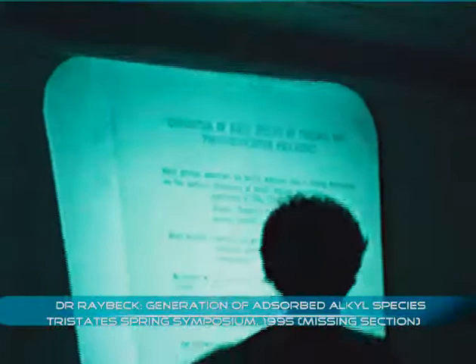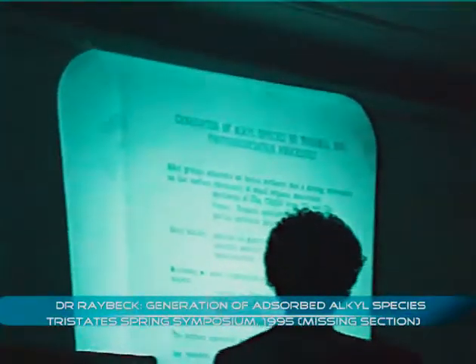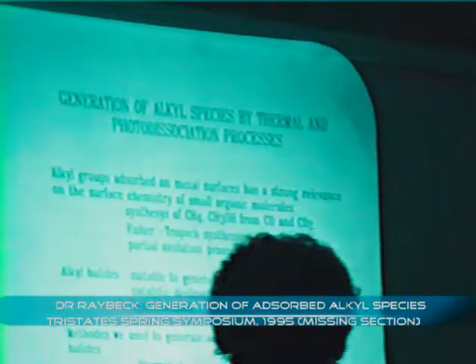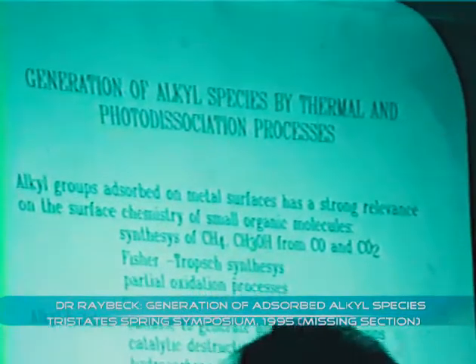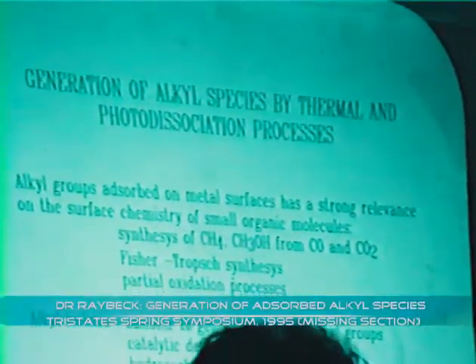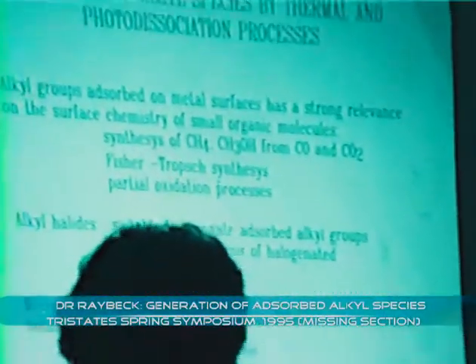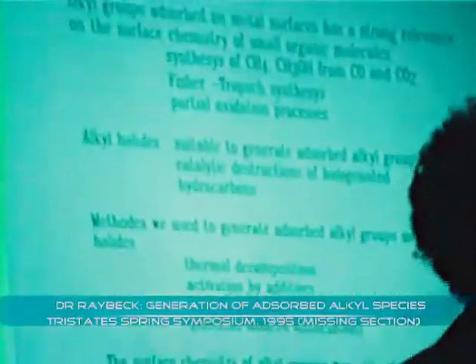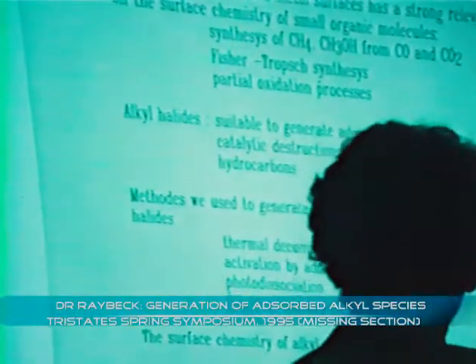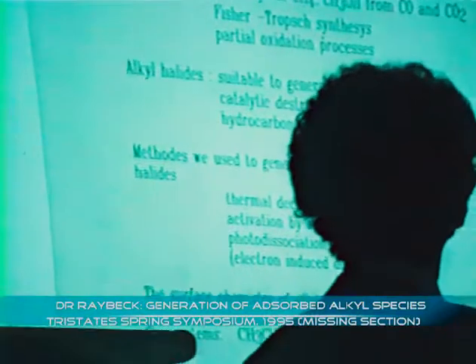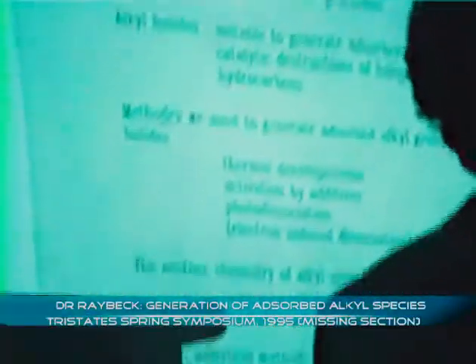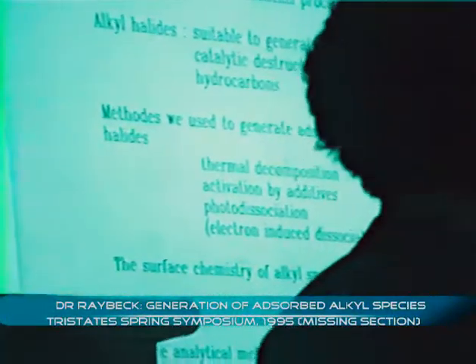Mr. Chairman, ladies and gentlemen, my lecture deals with the generation of alkyl species on palladium surface. Alkyl groups are important in many reactions. We produce alkyl species by the dissociation of alkyl halides. The other importance of alkyl halides is the catalytic destruction of halogenated hydrocarbons. We use thermal decomposition, photodissociation, and chemical activation methods to generate alkyl species.